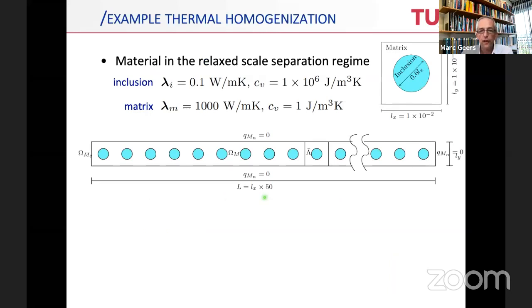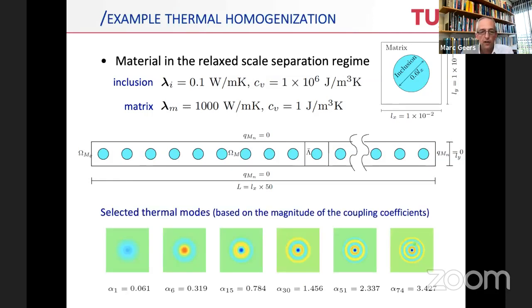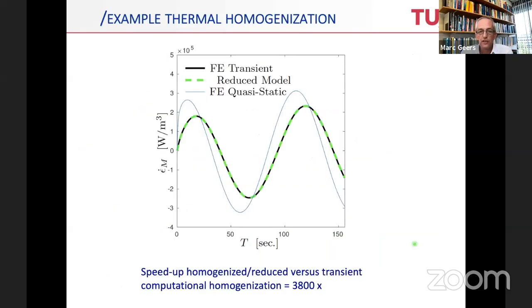A little illustration. So this is a problem where we have a clear contrast between the lambdas of the inclusion and the matrix. So we're definitely in the relaxed scale separation regime. We look at an array of such problems, matrix with inclusions. And we select the thermal modes, again based on the magnitude of the coupling coefficients in the constitutive equations. And once you've done that, you can again compare with transient solutions, the finite element transient, that's this one here, which is the full-blown solution.